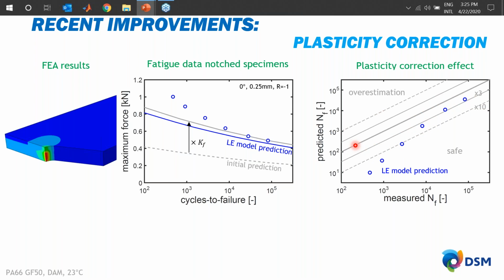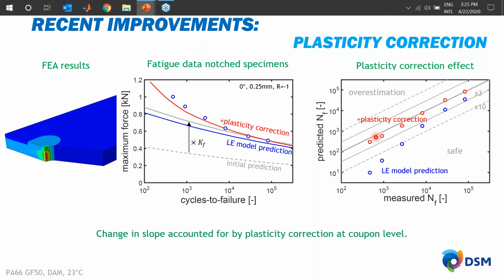But simply by applying an elastoplastic material model, we are already immediately spot on also for these kinds of local stresses without any recalibration, just giving it some kind of yielding, and then the entire performance also improves, as you can see over here. So the change in slope is actually accounted for by plasticity correction on coupon level.